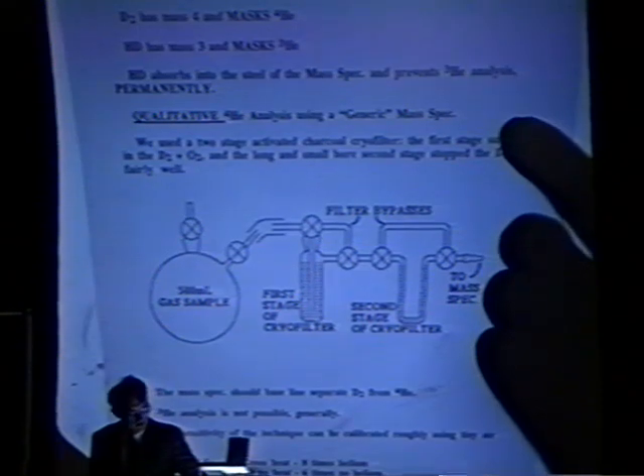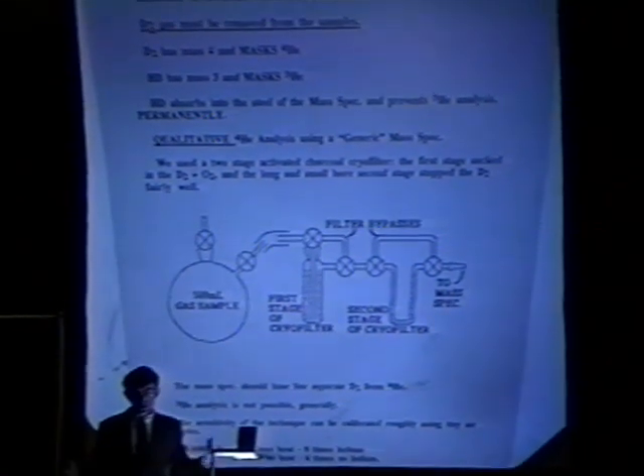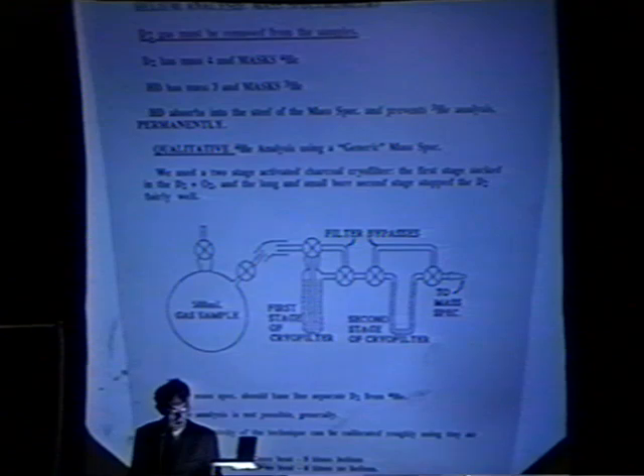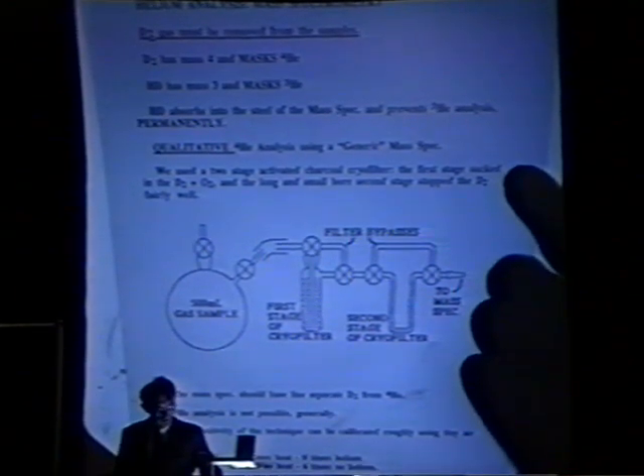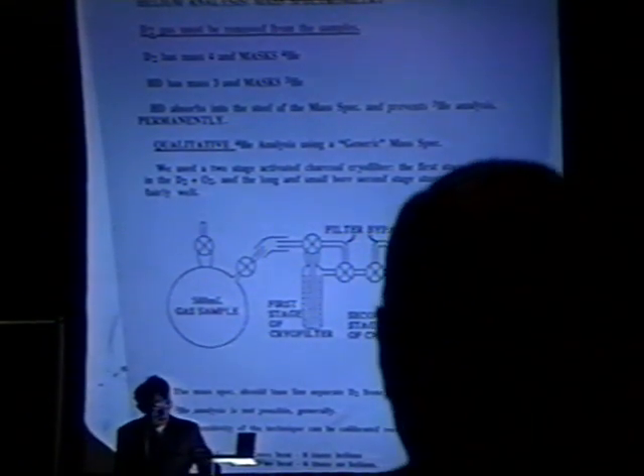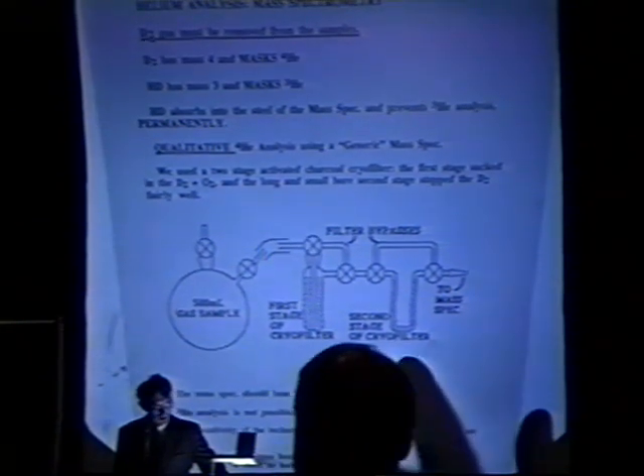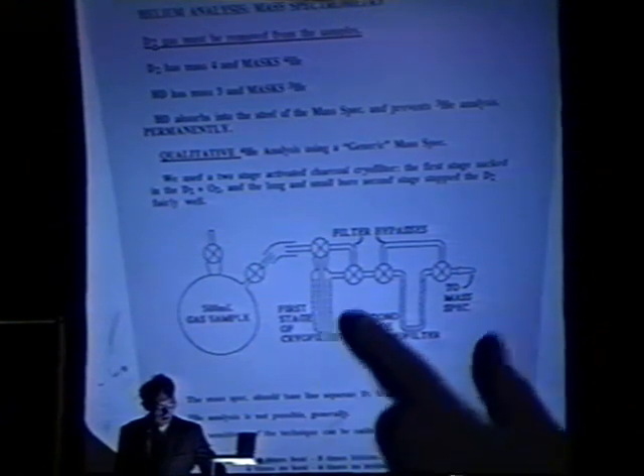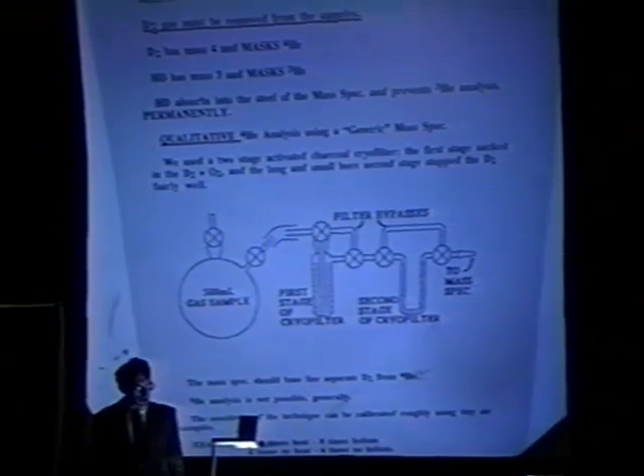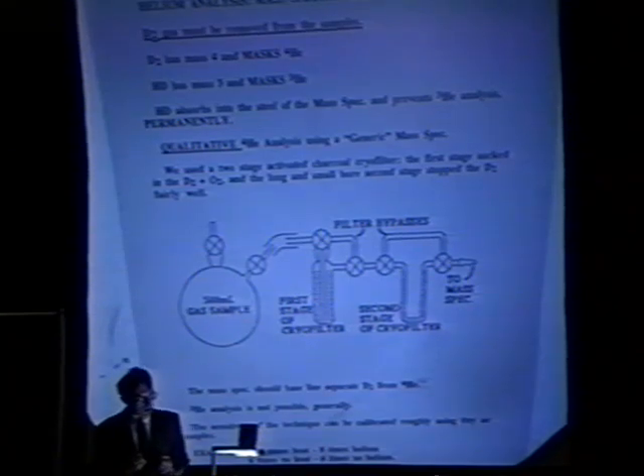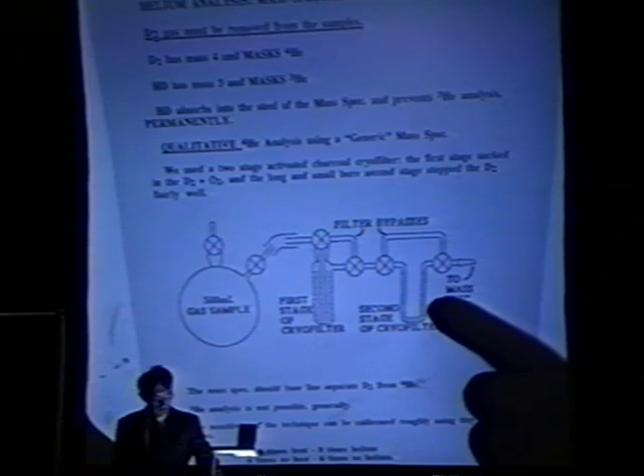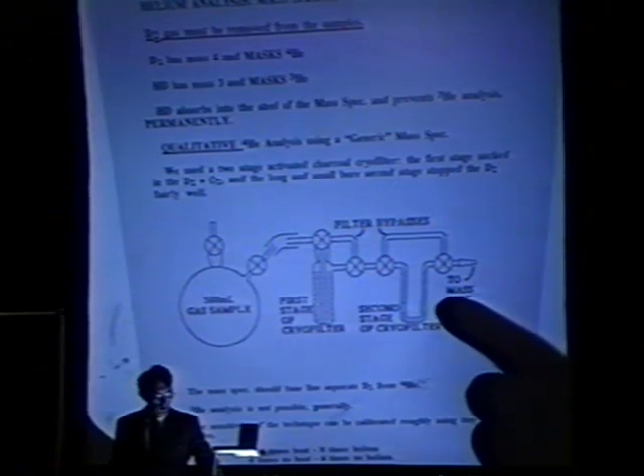You can do a qualitative mass spec just with generic mass spec. This is what I did at University of Texas originally. We just took the mass spec that was there and used it. What I developed was a two-stage activated charcoal cryofilter. The first stage sort of sucked the sample in. It was liquid nitrogen-cooled activated charcoal. It sucked the sample into the filter system, and then I opened it to filter it, cleaned it up further.